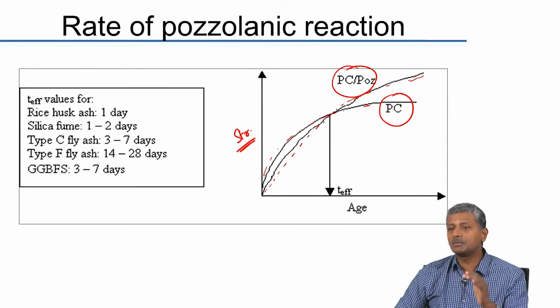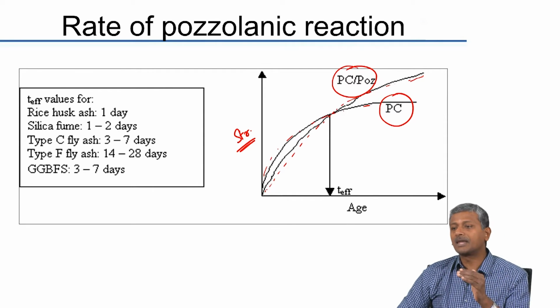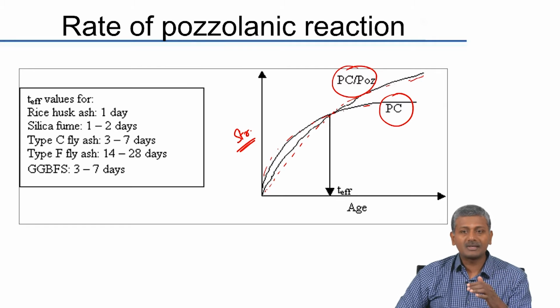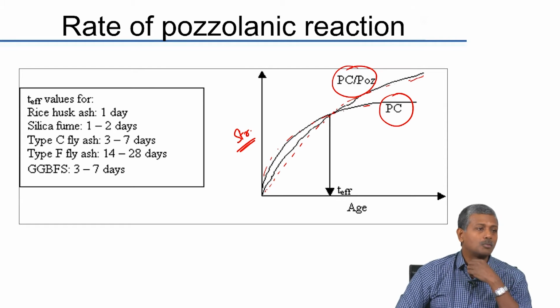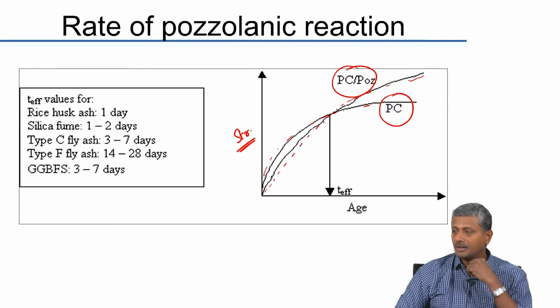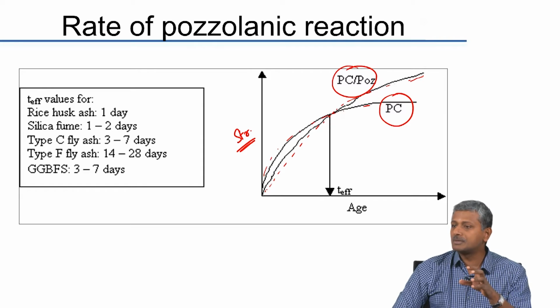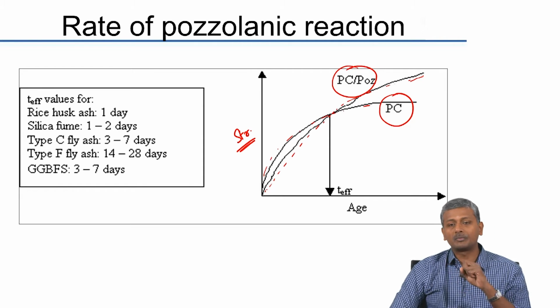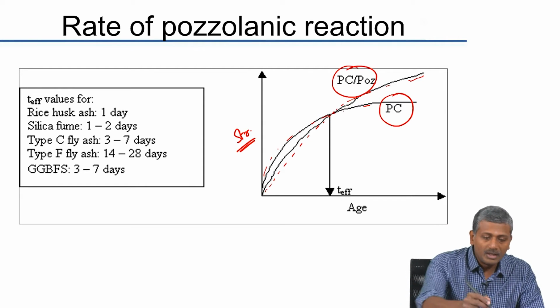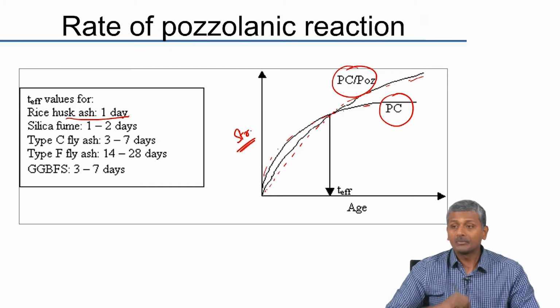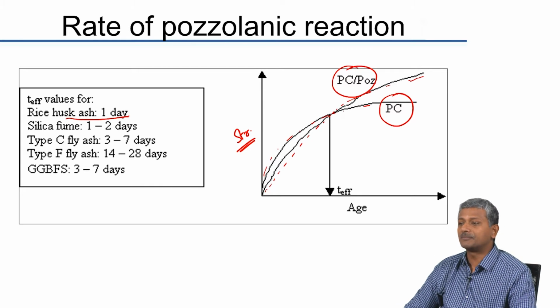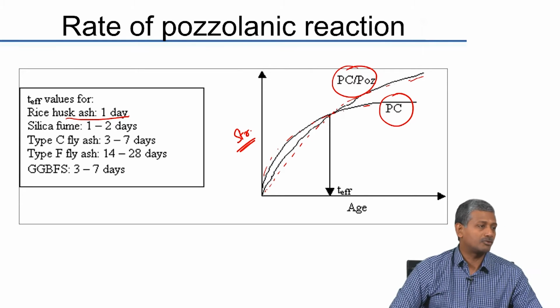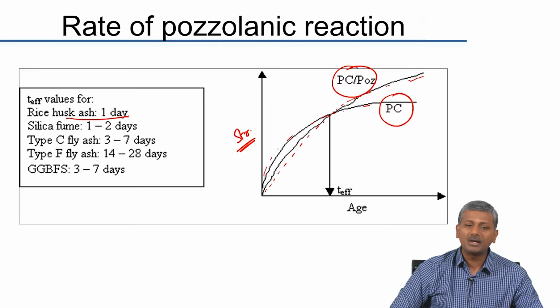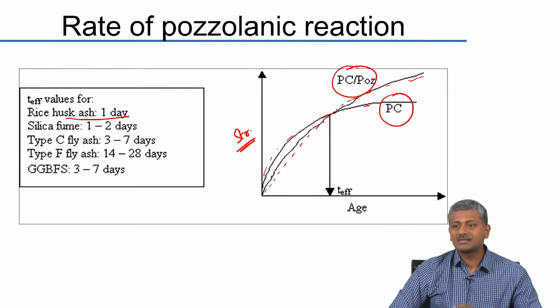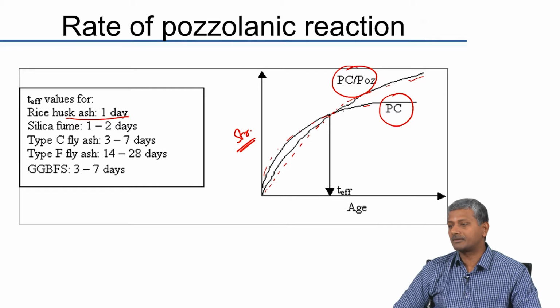So, potentially the pozzolanic replaced systems have the potential of increasing or overcoming the strength of your Portland cement based systems. Now, the age at which this happens is determined by the reactivity of your pozzolanic material. For example, if you say rice husk ash, I told you earlier it is about 90% silica. So, it is a high reactivity pozzolan. So, it may take only about 1 day for the mix with rice husk ash to attain the same level of performance as your Portland cement mix.